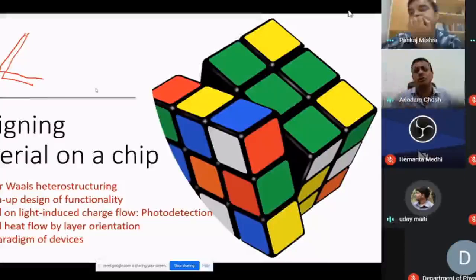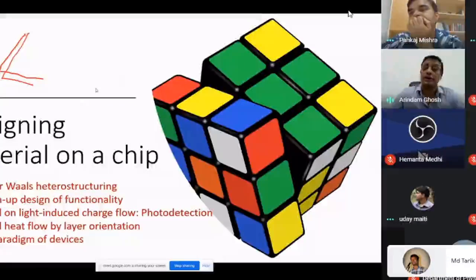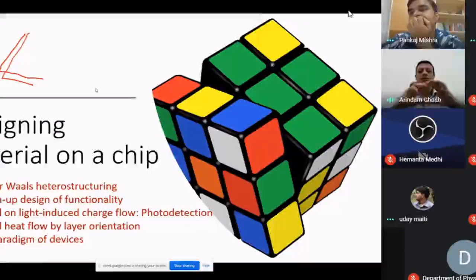So it's kind of remote interfacial scattering, you mean? The defects in boron nitride, no. That is defect because the boron nitride encapsulation is a bulk, in the sense about 10-15 nanometer thick boron nitride. So there are bulk defects in that. So those defects essentially start scattering electrons which are in graphene. Yeah. Thank you. Thank you.